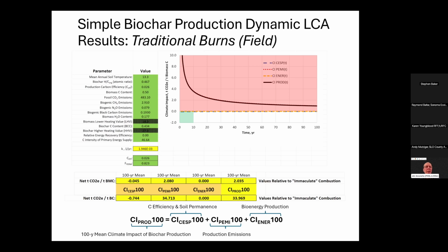And then we look at the water content of the biomass. The biochar carbon content in this case is about 43%. But these last 6 or so are really not incorporated because these are mainly for bioenergy, and we don't have any bioenergy going on. So on the right is a demonstration of how the three, well, let's go to the bottom first. We have this term called climate impact of production over 100 years. And that's equal to the sum of 3 different components: carbon efficiency and soil permanence, production emissions, and bioenergy production. With this study, there's no bioenergy, so that's always 0.